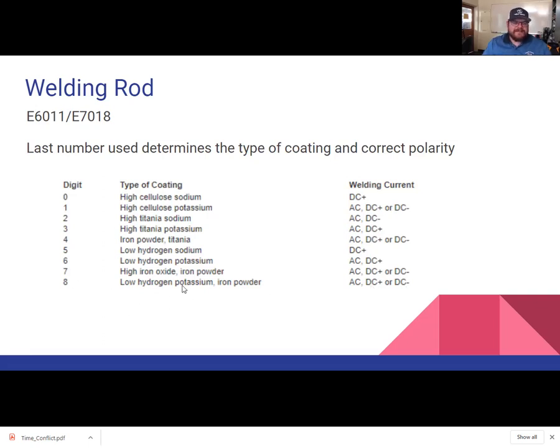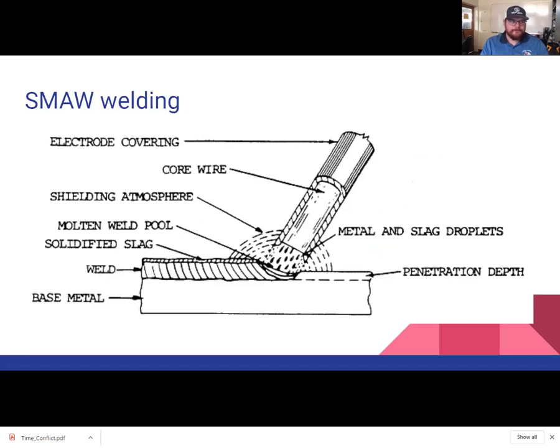Now, that 70-18 rod is what we consider a low hydrogen rod. And hydrogen in a weld is a bad thing. We don't want those. We actually store these 70-18 rods in an oven to prevent ambient moisture from collecting in those rods and then destroying our weld. We're going to get a thing called porosity. When we start talking about evaluating welds, we'll see some of that porosity. I think this PowerPoint has a little bit of that. And then when we go into lab and we start talking about evaluating, I'll show you what that looks like as well. Hopefully I can find some examples in person.